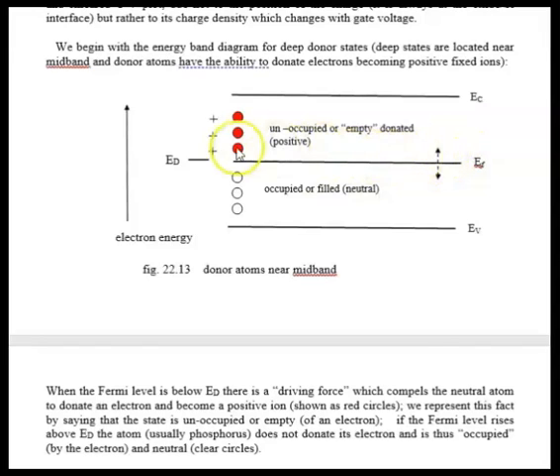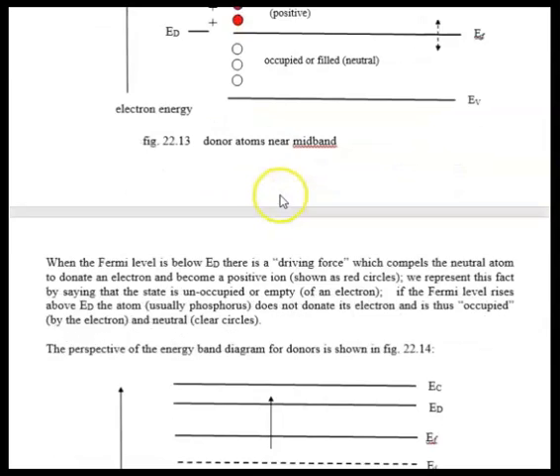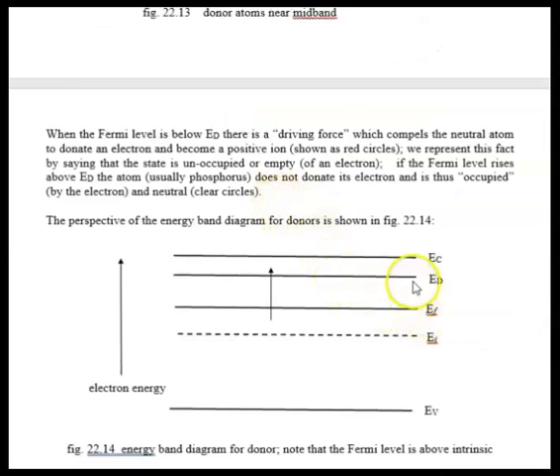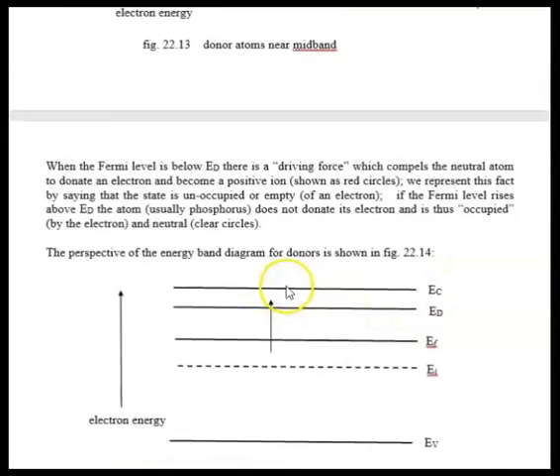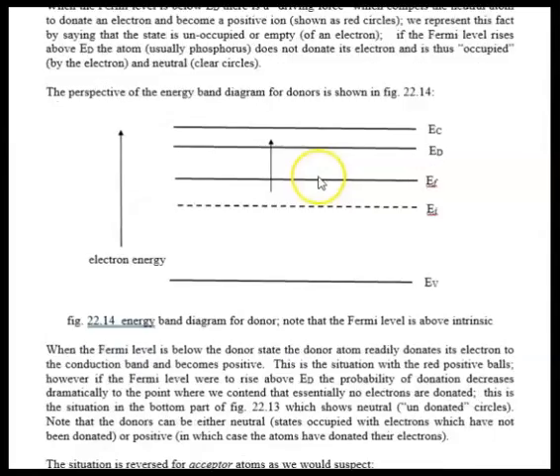As the Fermi level is above the electronic state, then the atoms are neutral. If the Fermi level is below the electron states, I would add more of these positive fixed red-filled circles. So if the Fermi level falls, more red circles. If the Fermi level rises, more unfilled circles. And that's exactly what is shown here. The electronic state stays constant, Fermi level rises up to here, the donation stops. When the Fermi level is below the electron state, then there is donation, and there are positive fixed ions.